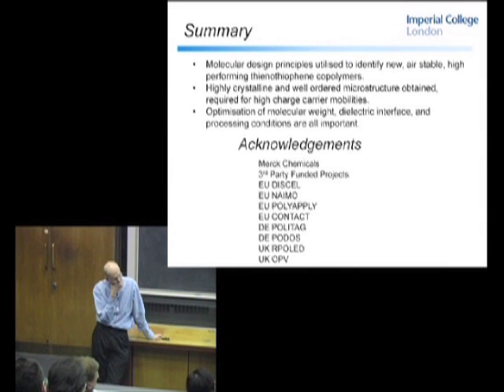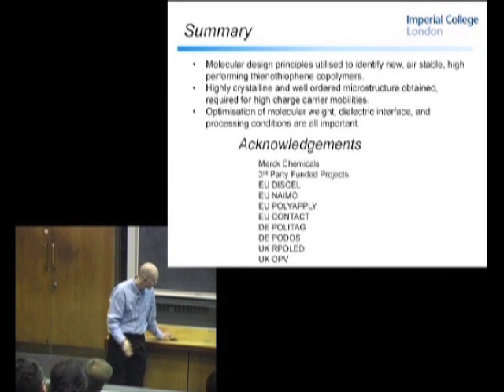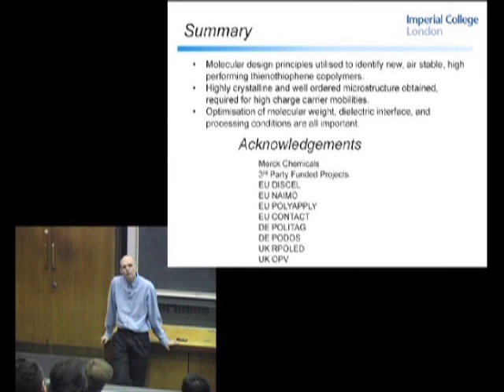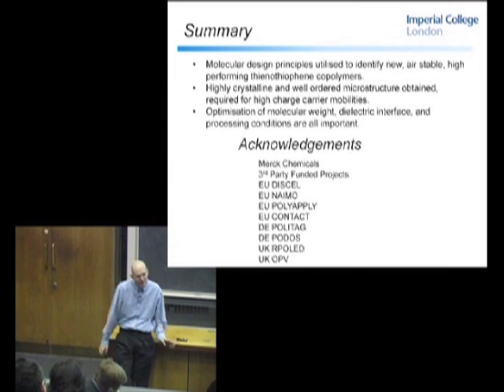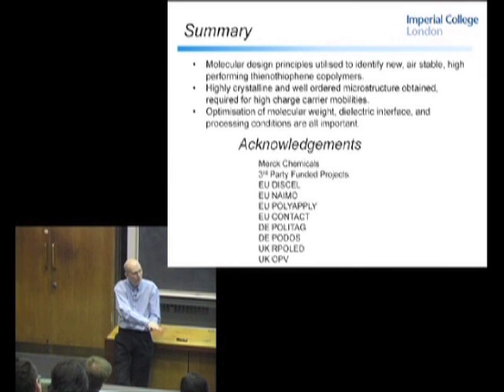Can we be thinking in terms of electrons and holes in this material like we do in conventional semiconductors? Well, yeah, these materials will conduct electrons, not quite so easily. There was a paper by, I think it's Peter Ho, who's now moved to Singapore, and Henning Sirringhaus and Richard Friend and the Cambridge guys, that showed that it was clear this was the reason. They had a silicon dioxide dielectric, which they treated completely with a hydrophobic alkyl silane, and they removed the traps. And if you remove the traps, then you get electron transport in most of these organic materials.